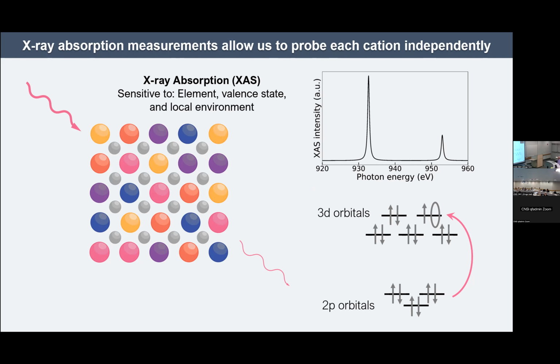A characteristic X-ray absorption spectrum looks like this one here, where this is an excitation of a 2p electron into a single unoccupied 3d state. This would be equivalent to copper 2+ with a 3d9 electronic configuration. This is known as the L edge, so this is the L3 edge and the L2 edge. The fact that there are 2 peaks here is because there's a spin orbit splitting of the 2p orbitals. So from a measurement like this, we already learn a number of things.